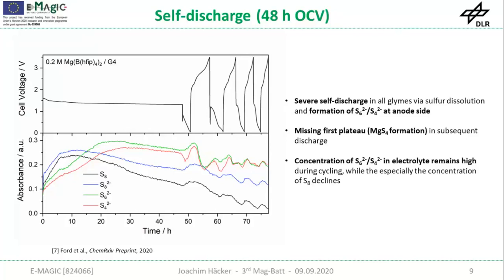If you have a look at the first plateau in the subsequent discharge, this is completely missing. So MgS4 formation has already taken place, and no capacity can be gained from that. In the subsequent cycling, the concentration of the short chain polysulfide is rather stable at a high level, while the elemental sulfur concentration declines. So there are all polysulfides present in the electrolyte.